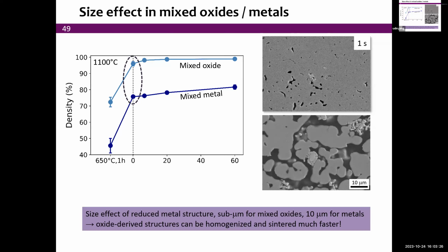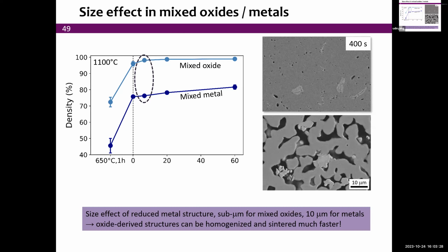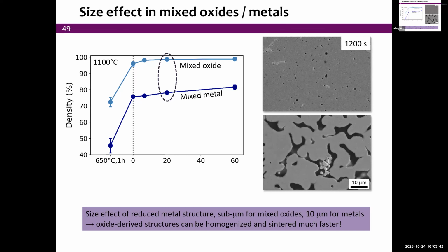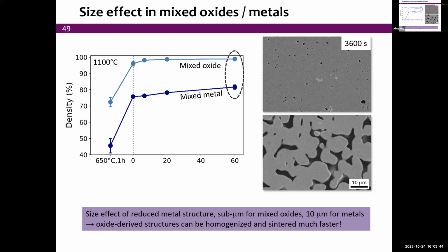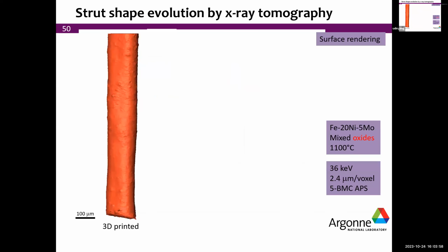And as we increase the time at 1,100 degrees C, we see a very good sintering here. And this kind of steady state amount of porosity. And it's very, very hard to sinter essentially pores that are 10 micron in diameter. It would take a really long time, really high temperature. And so we never reached that point, even though we are at 1,100 degrees C for about an hour. It's getting a little better, but it's still very open. You'd have to do much higher temperatures to get rid of this. So this is the oxide precursor. This is the metallic precursor. We see a big difference in that particular case.